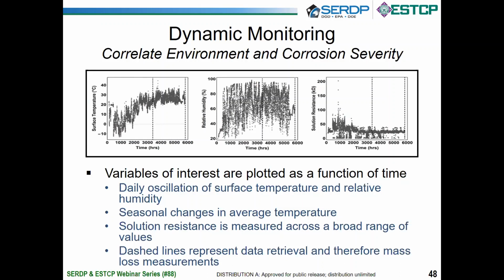As you can see, for the relative humidity, there's large amounts of variability, even day to day, which turns out to be a very important factor in what we're thinking about when designing new accelerated corrosion testing. Like Jim mentioned before, the cycling of relative humidity plays a very large role in the way and the severity to which corrosion can occur. If you look at the surface temperature graph, you can also see a record of changes in seasonal conditions. So with this, we get a really good picture of what exactly the system was exposed to.